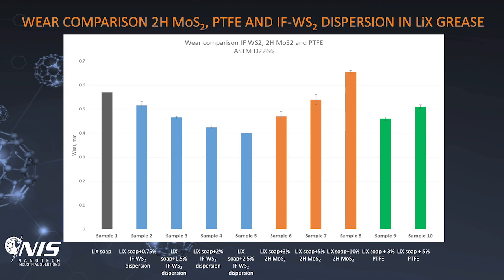And it's a very interesting plot of IFWS2 versus molybdenum disulfide. Molybdenum disulfide, because of the size and shape, is known as a very good anti-wear reduction solid, but primarily for low speed applications. But 4-ball is not a low speed application, it's a high speed application. Thus, you can see an increase in wear. So it's very important in what application you're applying your nanoparticles or micron particles or just any particles. It's not a panacea, it doesn't work for any application. So you need to be very careful applying the material to the right application. That's why you see an increase in wear with molybdenum disulfide. If we would increase the load and reduce the speed, you would probably see a decrease in wear as well.